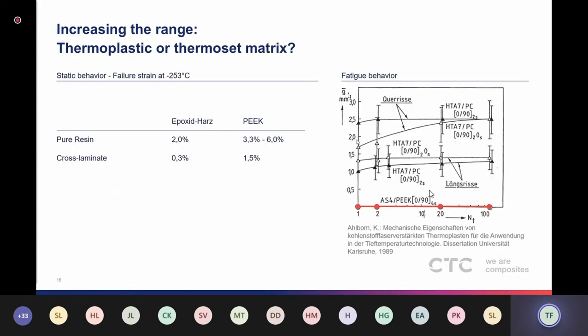The second technology we at the CTC want to pursue is thermoplastic materials. There have been investigations showing that at minus 253 degrees Celsius, PEEK has a much higher failure strain compared to epoxy resin.